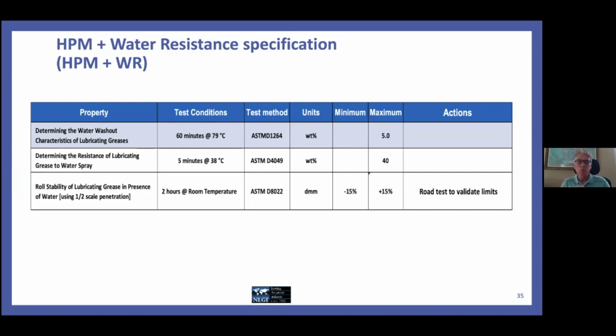This one is more of a wet adhesion test, and there was considerable discussion around the appropriate limit here. There was a lot of energy around having a 20 or 30% maximum limit, and this is when I think we got into the discussion of challenging but achievable. If you start specifying 20 or 30% maximum, you're probably talking about something like a steel mill grease or perhaps a paper machine grease where spray off is a serious issue.